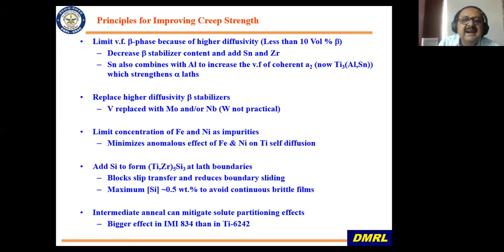And the other problem with near alpha titanium alloys is that you have to restrict iron and nickel like anything. You have to be at the ppm level. I'll show you the effect, but it really spoils the creep properties, and that is why titanium sponge with very low iron and nickel is very rare in the international market. These levels are very low. Let me show you how much.